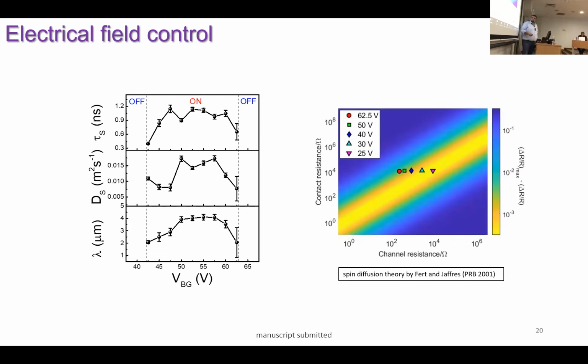I don't have time to go into detail, but we did some basic simulations, and it looks like it's all about the competition between the spin conducting channel material's conductivity versus the injector electrodes' conductivity. So it's something called the conductivity mismatch problem. Whenever your contact resistance reduces considerably here, even though your device is conducting very well, you cannot effectively inject any spin current. Therefore, you cannot measure any spin transport.